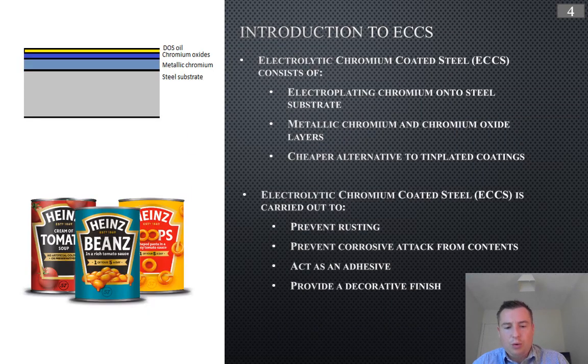So a little introduction to electrolytic chromium coated steel. I'm going to call it ECCS from now on. In simple terms, what it consists of is electroplating a chromium onto a steel substrate. This is done via electrical current through a series of chromate acid solution tanks. The steel substrate is typically around 0.5 millimeter thick, and the chromium coating is typically up to a maximum of 20 nanometers thick, so very small.